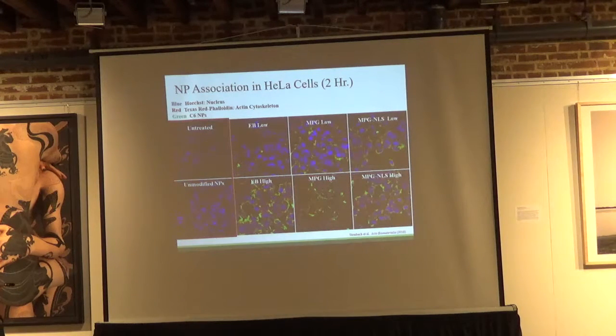We have untreated cells and cells with unmodified nanoparticles. On the left is controls. And here I show you what happens when we modify the surfaces of these particles with different cell-penetrating peptides at low and high densities respectively. And you can see from the green how much total cell association and also internalization is improved.